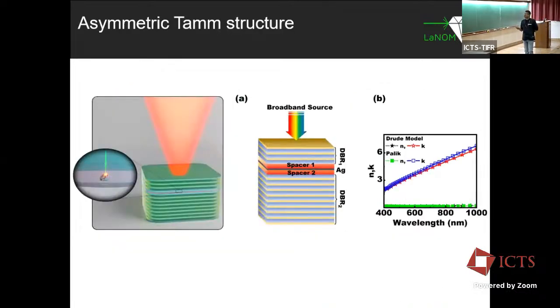So our idea was: you have a conventional Tamm structure, and you create a few more layers on top of that. We call this an asymmetric Tamm structure. Why? Because in the lower part you have a larger number of layers, and in the top part you have a few layers. So it's not a symmetric mirror system, but rather an asymmetric system.